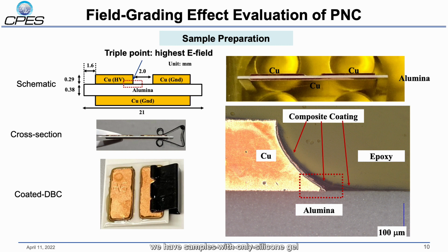We have samples with only silicone gel encapsulation. We also have this kind of coated samples. The black region at the edges of the copper is the coating itself. So to have a closer look at the coating, we made some cross-sectional samples.